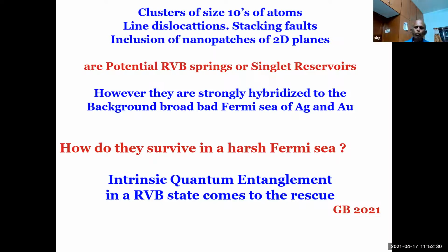And when you put them inside a metal, suppose I insert a chain of gold atoms in a 3-dimensional FCC lattice, I can insert it. They are very strongly hybridized to the background Fermi sea. So the gold will lose its individuality in terms of electronic property, even though structurally it's a chain, because the hopping matrix element is too large. So any local pairing tendency will be killed. Okay, so this is well known.